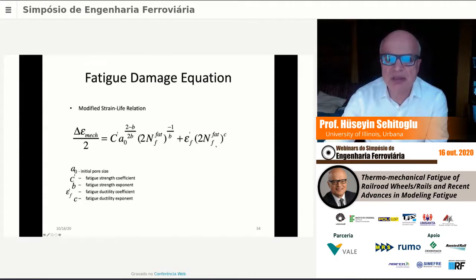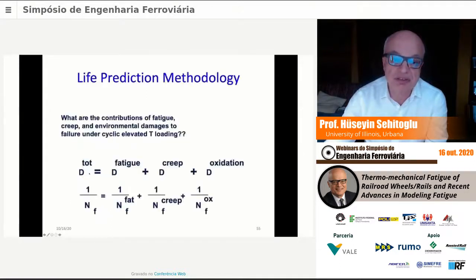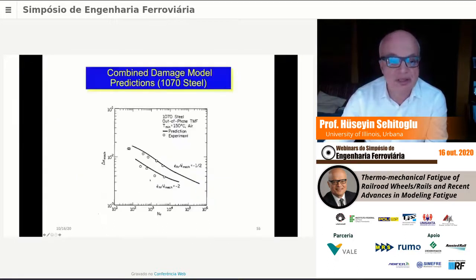The fatigue damage part is taken at that time to be pretty standard. This itself is obviously a very simple relationship, which we have subsequently worked on to derive from simpler, basic principles. But this is the Coffin-Manson model equation. This is the low cycle fatigue. This is the high cycle fatigue part. So at that time we summed the damage, fatigue, creep, and oxidation damage, and tried to predict the lives. That's mechanical strain versus fatigue life.